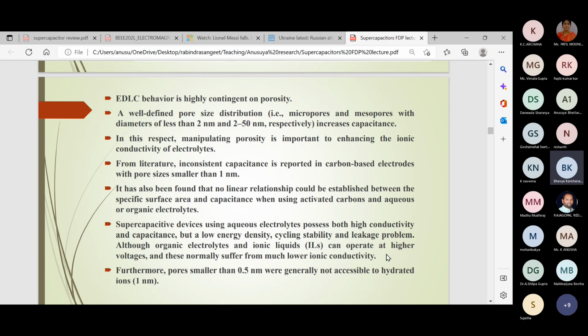And from literature, inconsistent capacitance is reported in carbon-based electrodes with pore sizes smaller than 1 nanometer. Because of the size of the ions itself: H2 is very small, of course, but SO4 has 4 atoms of oxygen, so it goes a little bit higher than an Angstrom. And then we talked about the solvation, where you've got the ion at the center, but you also have the solvent connected to it. So a bigger solvated molecule usually cannot penetrate pore sizes smaller than 1 nanometer. So even though you do a BET, a surface test, and find the surface area, pores less than 1 nanometer will not count towards capacitance.